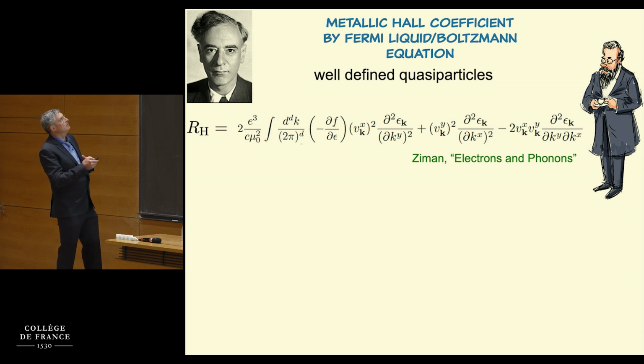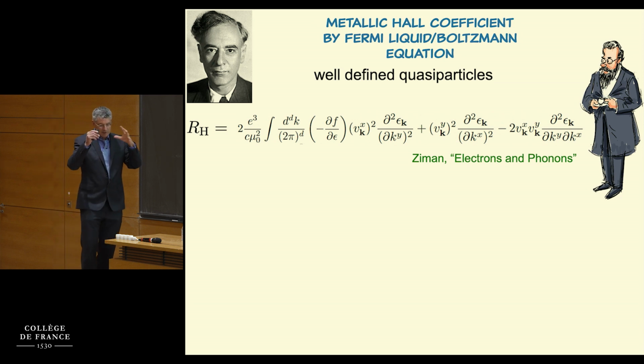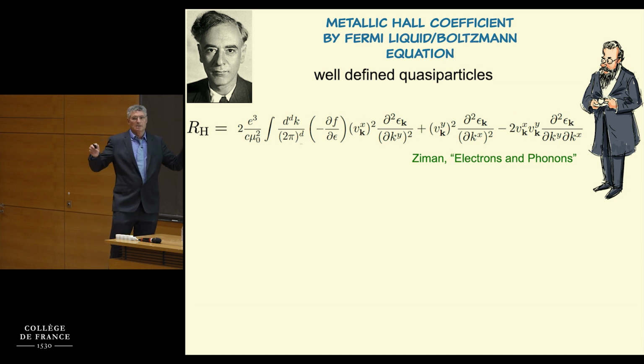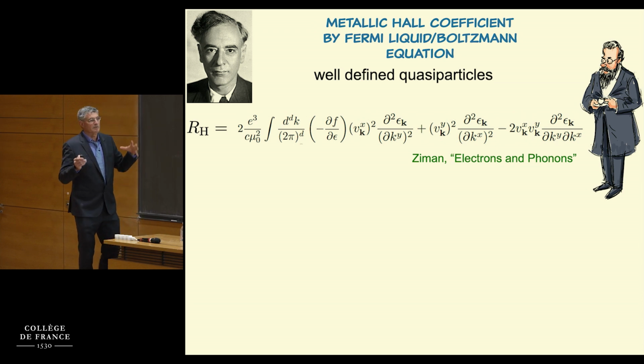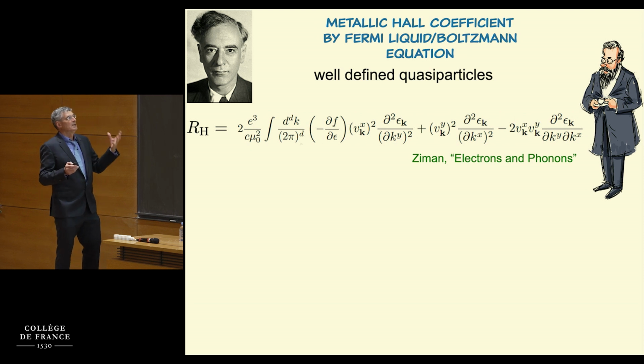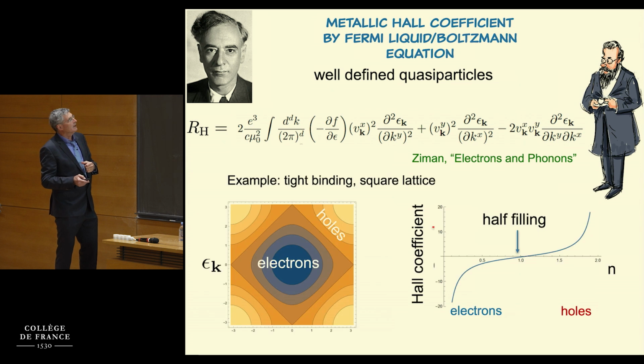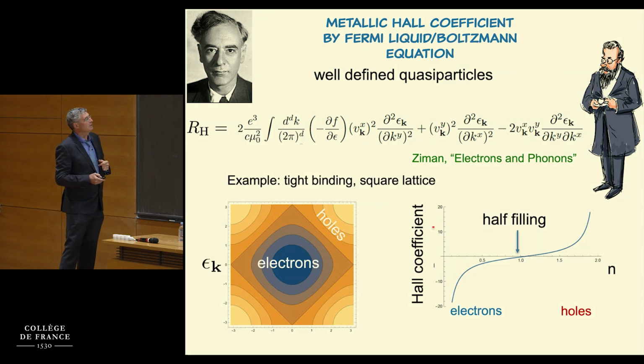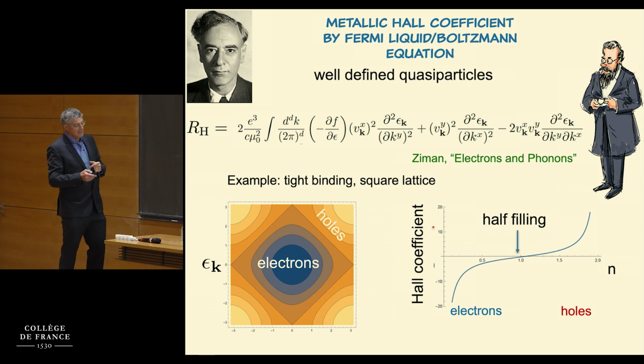And it will give you the sign of the Hall coefficient depending on whether the Fermi surface is a closed ball, or the sphere of the Fermi surface covers the empty sites. So you take a two-dimensional band structure, just a tight binding square lattice, and you'll see immediately that the Fermi surfaces are these curves. If you are filling the bottom states, you get electron-like closed Fermi surfaces.